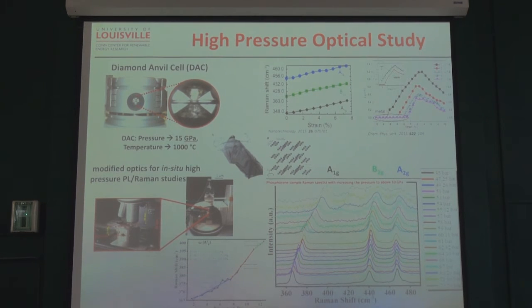When you pressurize it, you have to use some kind of gas, like we use argon gas. That gas pressure will increase the inside pressure, the pressure on the diamonds. You can then measure that pressure by the ruby luminescence peak.